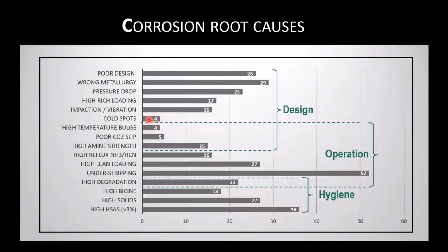Cold spots are an issue because wherever you have what we call a cold bridge, which could be a ladder to the side of a vessel, a manway, temperature probe locations, any of those can cool down the temperature of the regenerator or contactor, and that's a point where we get condensation. And if there's acids present, the acids condense on the metal wall and we have corrosion problems. So there's too many of these to go over, but typically it seems obvious that if we can regenerate the solution properly, design it correctly with the right metallurgy, and make sure that we don't overload the solution with H2S and/or CO2, we can eliminate a lot of our corrosion problems.